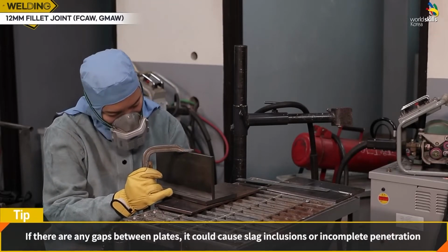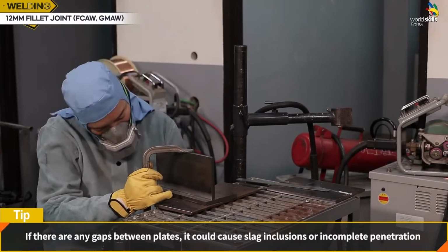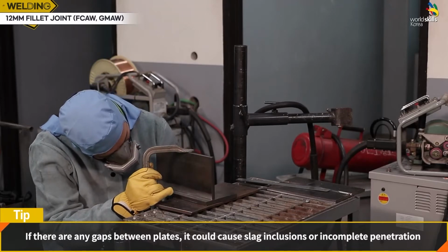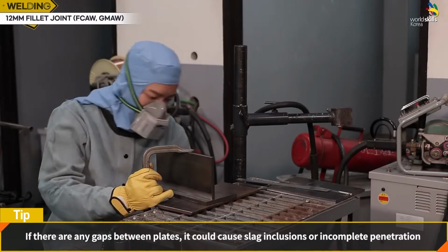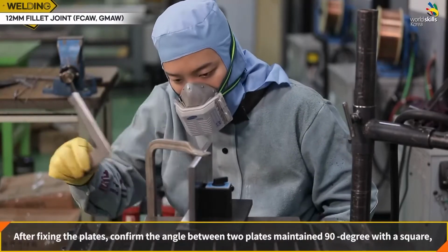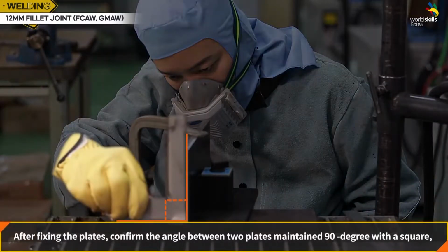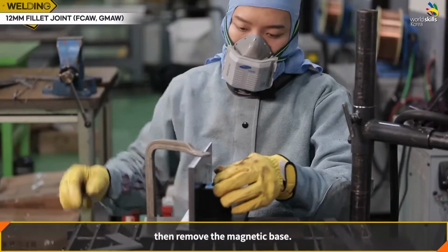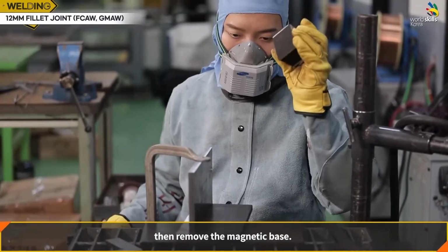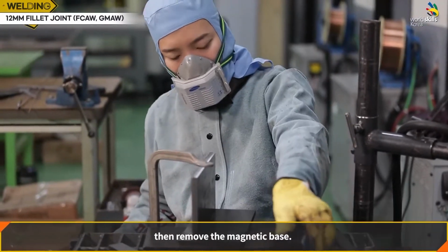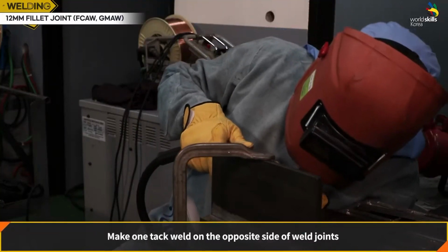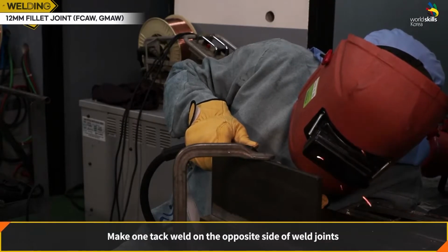If there are any gaps between plates, it could cause slag inclusions or incomplete penetration. After fixing the plates, confirm the angle between the two plates is maintained at 90 degrees with a square. Then, remove the magnetic base. 1-point temporary welding is applied to the back of the welding line.